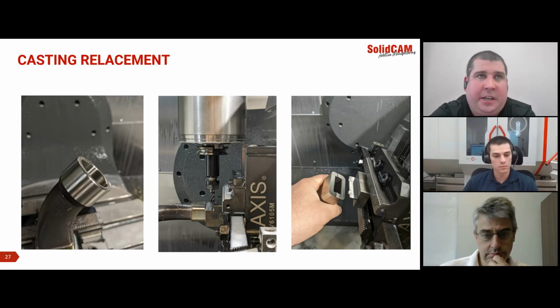And one of the things, and it actually ties back into distortion, what you don't want to do is, let's say, print from 0 to 15 degrees and then machine from 0 to 15 degrees and then start printing again from 15 to 30. You need to leave kind of a thermal barrier. That way you're not distorting what you've previously established.